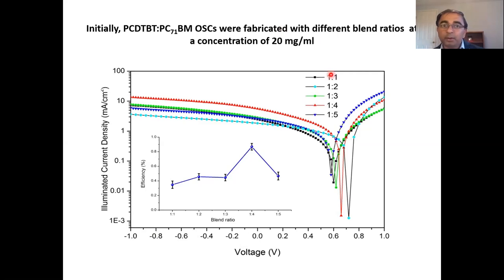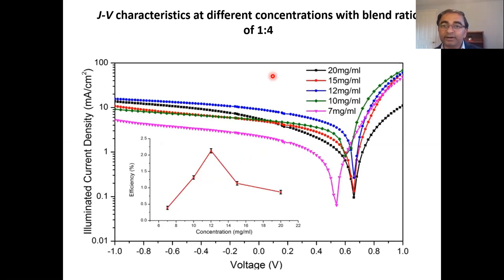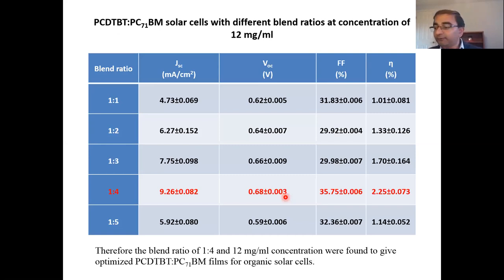Now we want to optimize this concentration also. For this, we have made solar cells with different concentrations, 20 mg, 15 mg, 12 mg, 10 mg, and 7 mg, but with 1:4 blend ratio. And what we observed is that at 12 mg per ml concentration, we get the highest efficiency compared to other concentrations. So what are our optimized parameters? 12 mg per ml and 1:4 blend ratio. And there is a table for this.